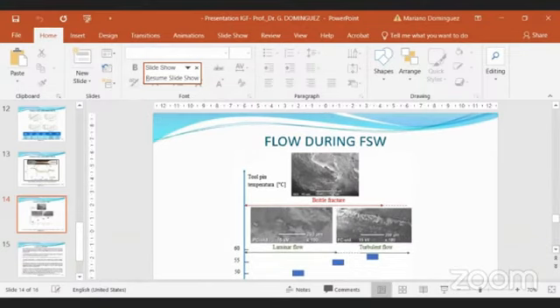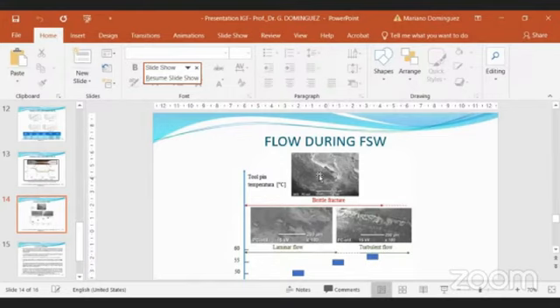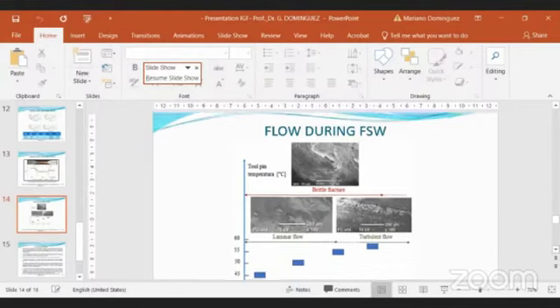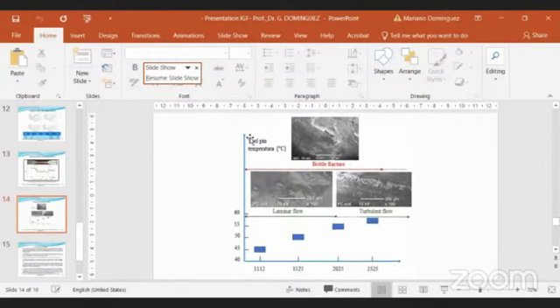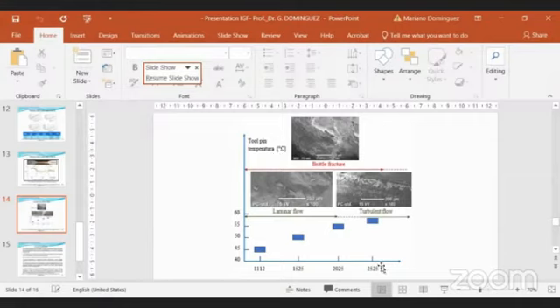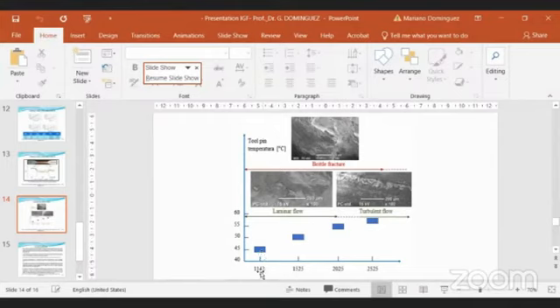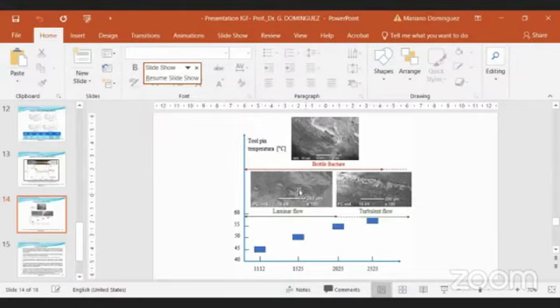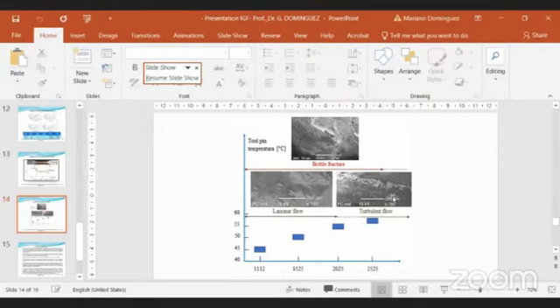Finally, the flow during friction stir welding. All specimens present brittle fracture for all the combination of testing conditions. But concerning the flow, the vertical axis shows the tool pin temperature in Celsius degrees, and in the horizontal axis, the different nominations or specimens. You can see that for the lowest values of rotational advance speed we have the lowest values of tool temperature. Then we observe a laminar behavior of flow inside the testing specimen. When we increase the rotational speed and the advance speed, a transition to turbulent flow is observed.